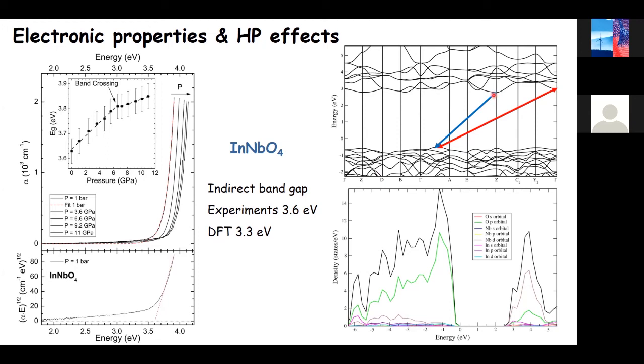This one is the absolute minimum, but as we start increasing pressure around 3 GPa, this one becomes the absolute one. And this is what you can see here. There is a band gap crossover. Here we have one minimum dominating, and here we have the other minimum dominating. But again, in spite of this band crossing, there is a blue shift of the band gap with pressure.